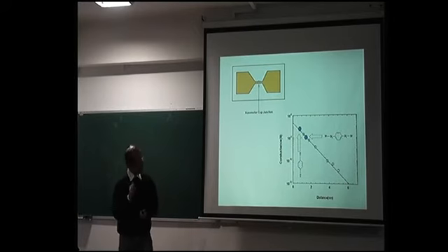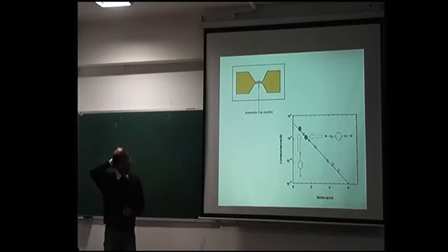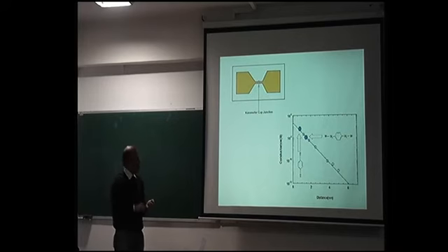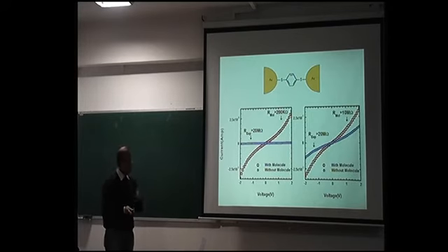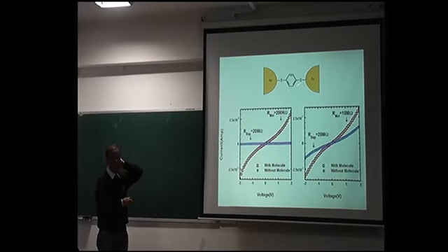So what do you do? You first check with this conductance. From this conductance, you estimate the gap and see whether it is less than 5 nanometer. Then you select those chips where you have a gap of less than 5 nanometer, and put this molecule in, and you can get IV characteristics. You can get IV characteristics of a single molecule, but there is a doubt: how do you know that there is a single molecule or there are 10 parallel molecules?